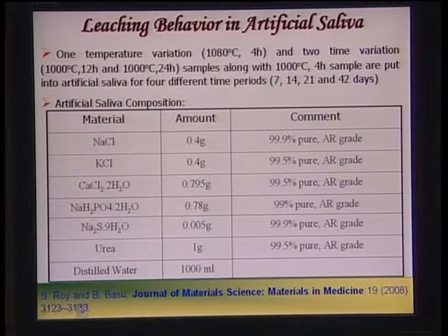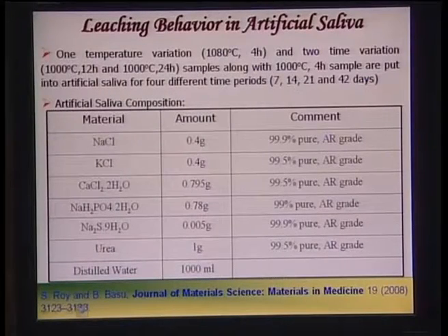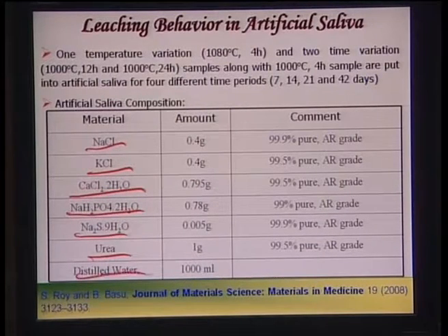Now, in order to assess whether these glass ceramic materials have good in vitro biomineralization property, this was assessed by immersing them in artificial saliva. Artificial saliva closely simulates the oral environment. Oral environment means inside the mouth, the content of this aqueous environment, and that is what has been mimicked by artificial saliva. What does this environment look like? You have NaCl, KCl, calcium chloride, NaH2PO4, Na2S, urea and distilled water.